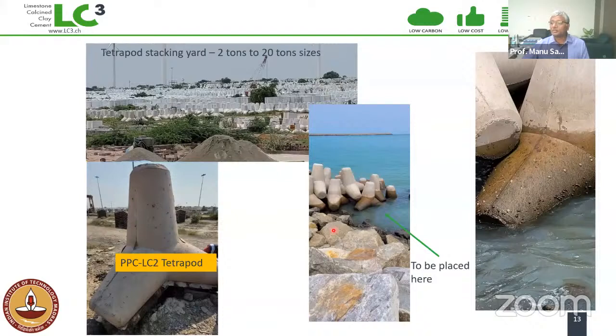You can imagine a tetrapod of 20-ton size, how many cubic meters of concrete it would take to really fill up that 20 tons. So 1 cubic meter is about 2.5 tons. So there's about 8 cubic meters of concrete in 1 tetrapod. And with so many of these tetrapods, if you have a 7-kilometer long breakwater, you can imagine the extent of concrete that is required and the amount of cement that can be saved by utilizing something like LC2 or LC3.